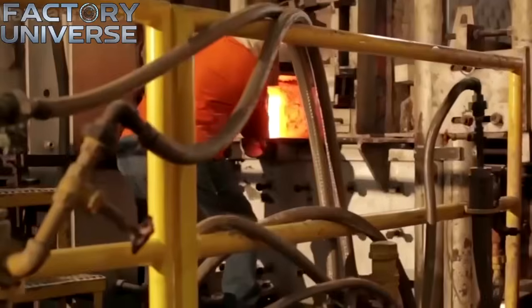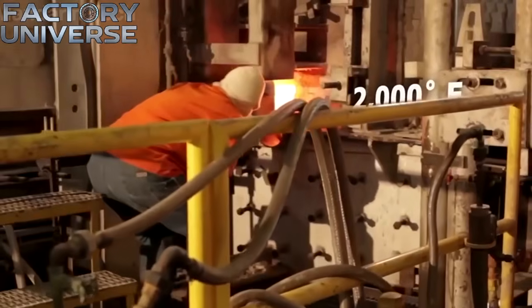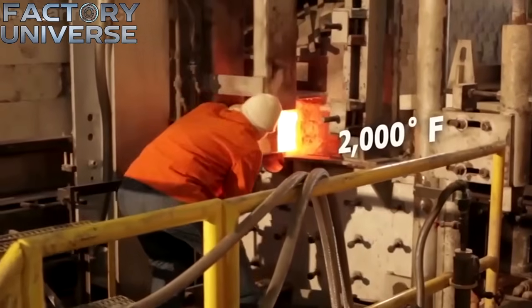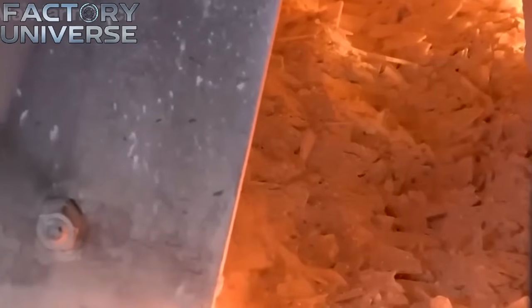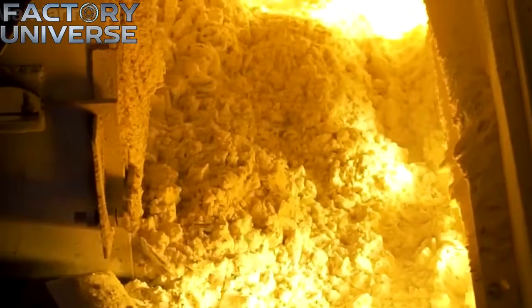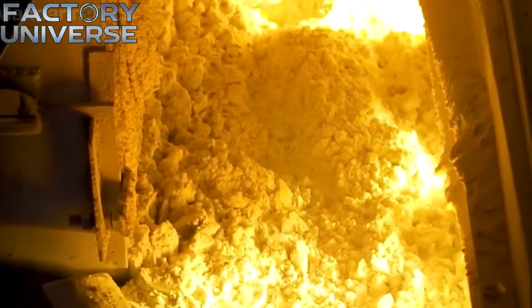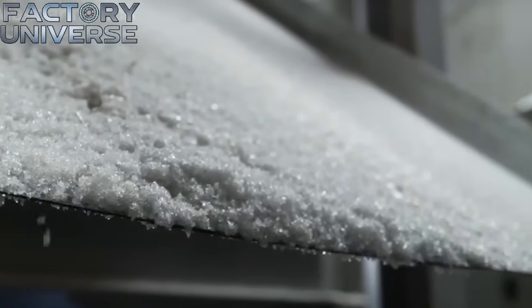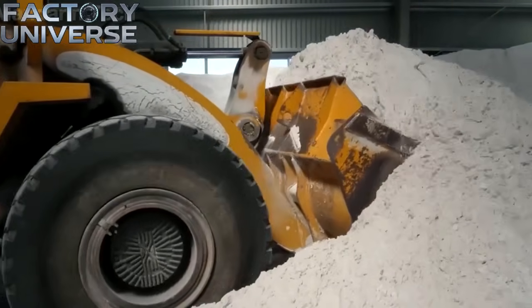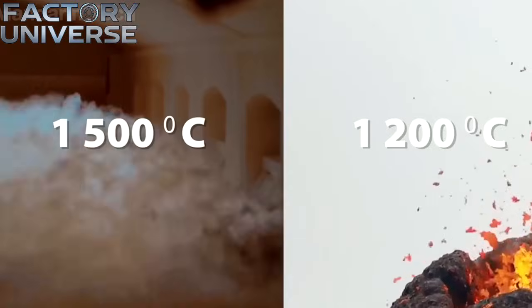Transition to the next level. 10% increases in cullet volume yield a 3% reduction in total energy consumption, while simultaneously decreasing carbon dioxide emissions. The use of recycled glass allows the melt to flow with greater fluidity, cutting energy requirements by up to 40% compared to batches composed entirely of virgin raw materials.